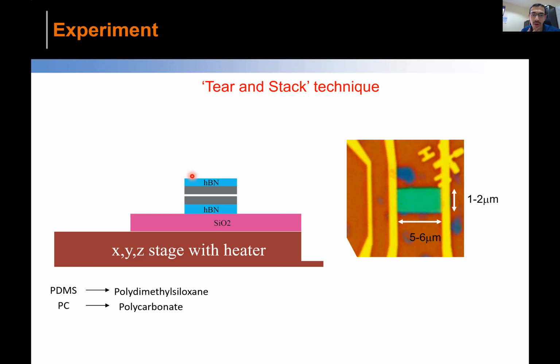But it takes quite a long time to achieve, particularly this magic angle. So it's trial and error. The yield is not that high. I would say it's less than 10%. So out of 10 samples, you will get one sample. Maybe we can discuss the difficulties and so on later.